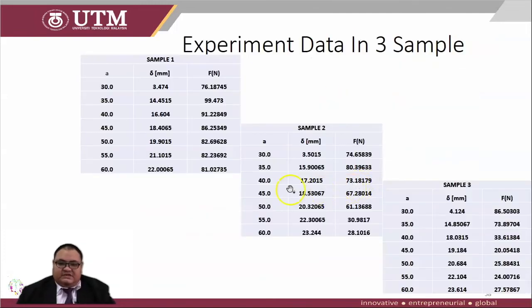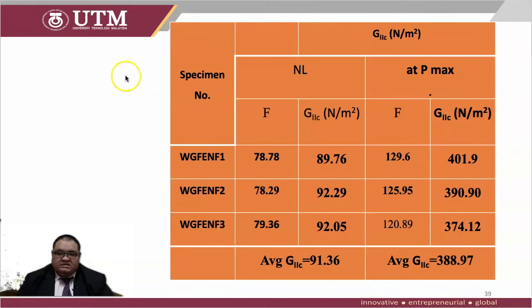This is the experiment data for 3 samples, with crack length A set at 30 to 60. In this result, this is G2 for non-linear and at P maximum, for sample 1, sample 2, and sample 3. And this is the average for non-linear, and this is the average for P maximum.